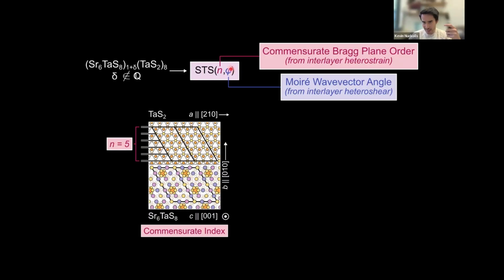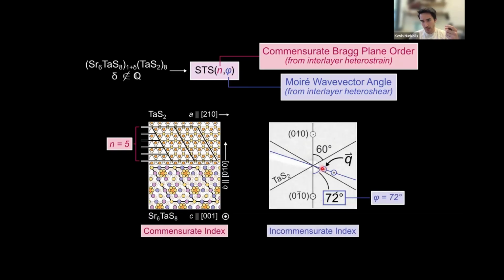And then the incommensurate index could be the wavelength of the Moiré superlattice or the length of the Q vector, but we decided to take the angle of the Q vector with respect to high symmetry directions, namely because it's really easy to read out through X-ray diffraction, but it's also much easier to say. And so with n equals 5, phi equals 72, we would call this Moiré compound STS 572. If you didn't understand that naming scheme, it doesn't matter for the rest of the talk. Just recall that STS means strontium, tantalum, sulfur. And if these two indices are different between two different compounds, they have different Moiré superlattices, although they're chemically identical.